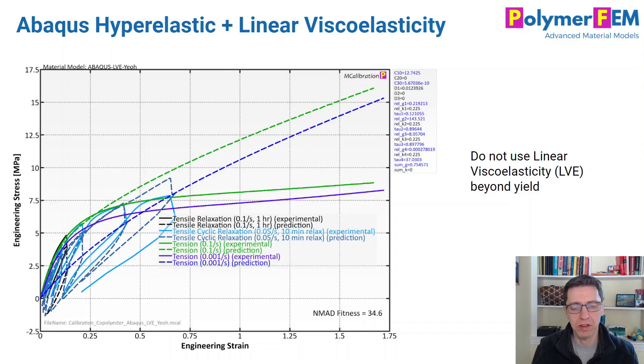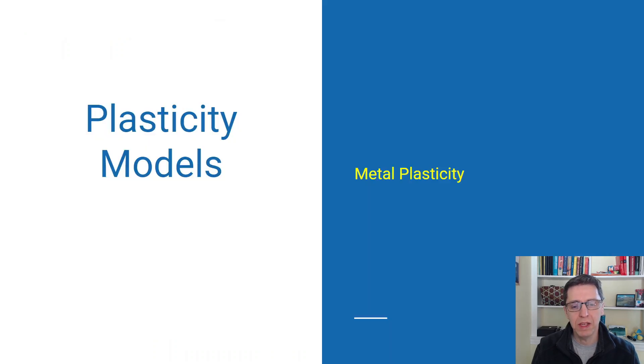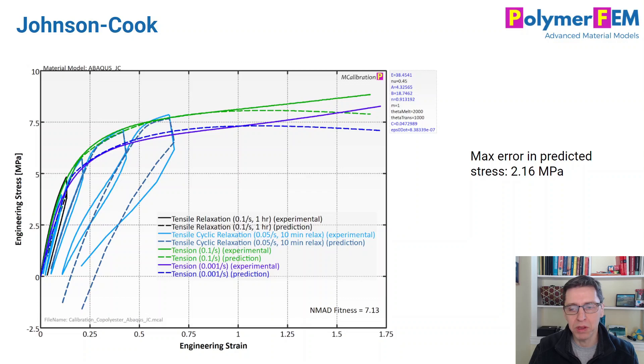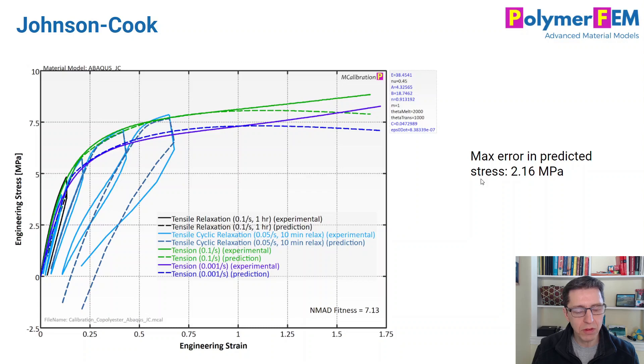So what can you do? You can try metal plasticity models. The Johnson-Cook plasticity model gives an average fitness of 7.1%, and the maximum error of any point is 2.16 MPa, which is a large fraction of the stress values of interest. So the maximum error is not good, though the average error is not too bad.